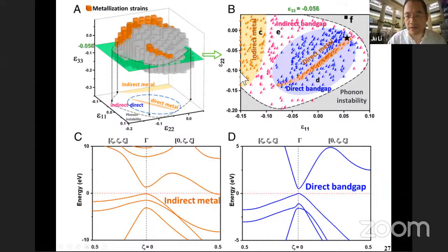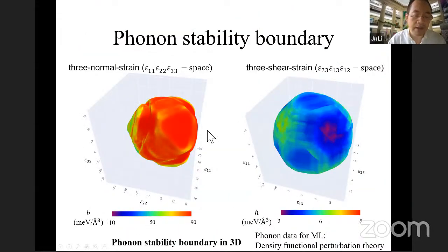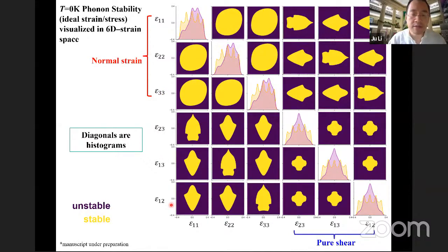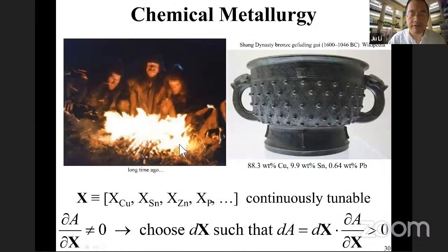And for diamond, as a function of strain, you can either have an indirect semiconductor in some regime, and then you can go to an indirect metal, or you can go to a direct metal or a direct semiconductor. So this is kind of like a phase diagram in the system, and we can predict the phonon stability boundaries. So not only the electronic band structure, but where the phonons may turn to have imaginary frequencies that actually define the lattice instability and the ideal strain surface. We're able to visualize it in the 6-dimensional strain space with machine learning. And this is a very powerful tool.